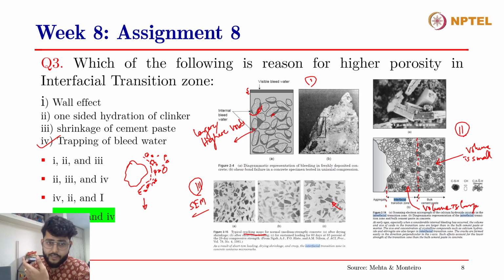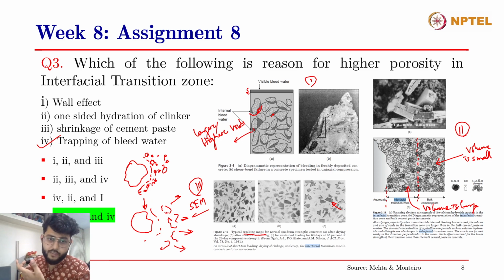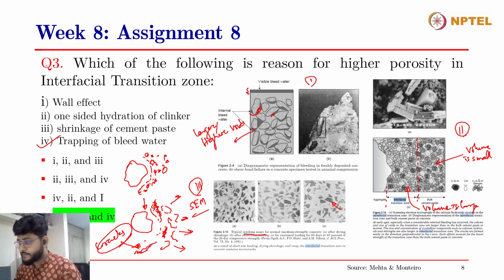Now that it has hydrated, this is the aggregate and this is the ITZ, but the cement grains are further pulled apart by the internal force due to the hydration process, due to the chemical shrinkage, and therefore these cracks arise at the interface between the aggregates and the cement paste, right? So these cracks at the ITZ also increase the volume of the voids, and therefore increase the porosity of the ITZ.